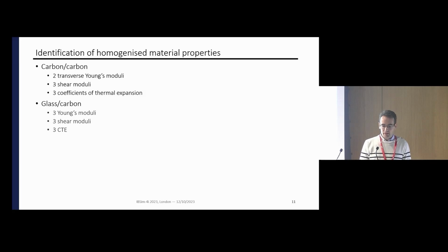And in the problem, as we only measure the displacement on the images, we don't have anything which is homogeneous to a force or a constraint. So we are not able to determine the moduli in an absolute manner. We can only determine the moduli to a factor.